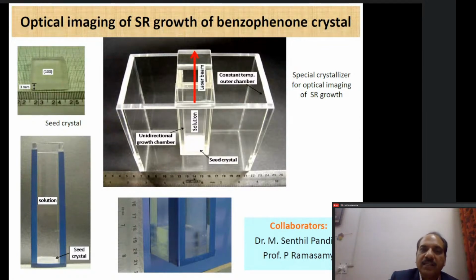So we made this apparatus, because usually the SR growth systems require a circular ampule, right? We have a cylindrical ampule which is put inside the growth chamber. But we can't use a cylindrical ampule for imaging, because once we put an expanded laser beam through a cylindrical ampule, it will focus the beam because it's a curved surface, right? So we have to make a model apparatus in which the side faces through which the beam will pass should be flat. So instead of a cylindrical ampule, what we devised was a square ampule, right?